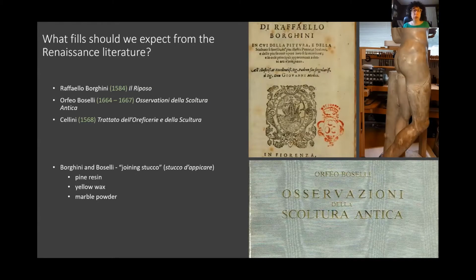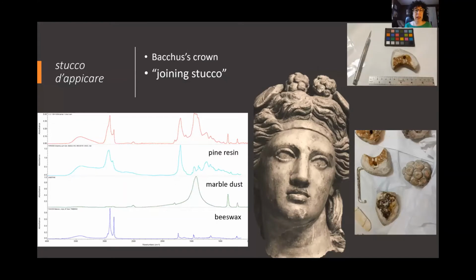So what type of fills would we expect in order to make these joins nice and smooth? Well, it turns out that the Renaissance literature, if we look at the writings, for example, of Borghini or Boselli or Cellini, give us lots of information about what these fills should be made of. They talk about a joining stucco that's prepared from pine resin, yellow wax, and marble powder. And that's just exactly what we see in the elements of Bacchus's crown, that the leaves and the berries are joined to Bacchus's head with a mixture of pine resin, marble dust, and beeswax.